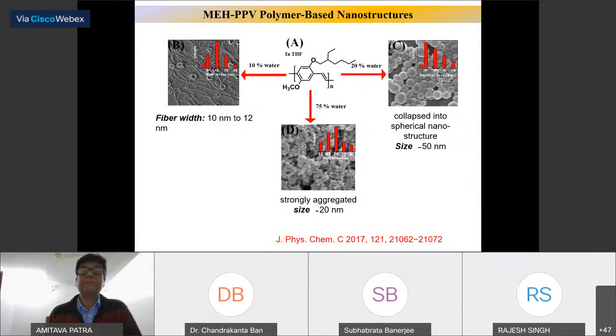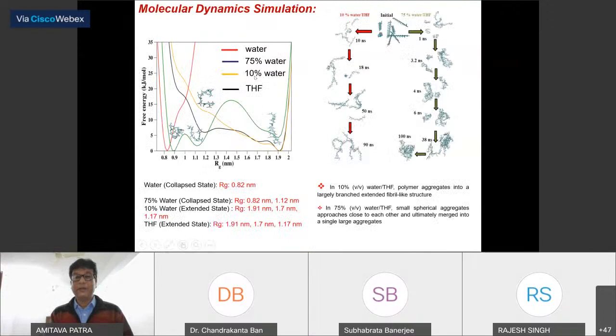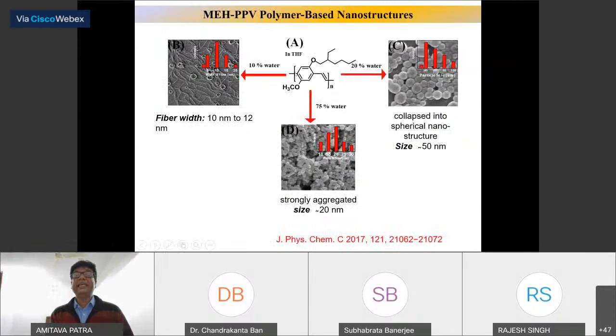Now I'll give you one simple example. This is MEH-PPV, that is a very important molecule for optoelectronics or OLED, organic light emitting devices. And here what happened, we have seen that if you put it in THF solution, because THF is a very good solvent for the polymer, but if you put in water, 10% water, you get the fiber-like structure. But if you have 75% or 20, this is the nanoparticle formation. We try to understand the mechanism of this, a very fast process. You cannot understand kinetically.